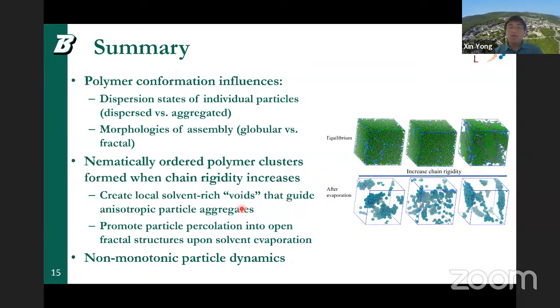And then the fundamental mechanism of this structure formation is because the polymer starts to develop nematic order, and then they actually cluster themselves in the presence of solvent first. And this creates local solvent-rich voids that will guide the anisotropic particle aggregates. And then the presence of these anisotropic aggregates will percolate into mesoscale structures upon solvent evaporation. And then we also developed the interesting non-monotonic particle dynamics due to the change in particle and polymer coupling, the coupling of their dynamics.